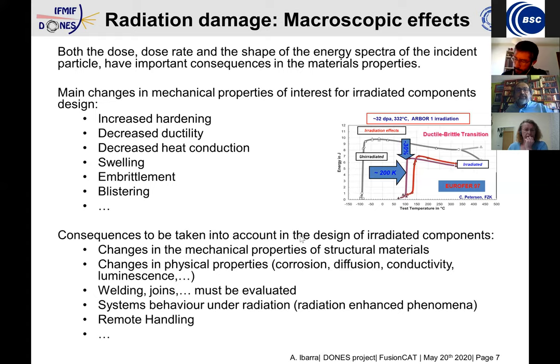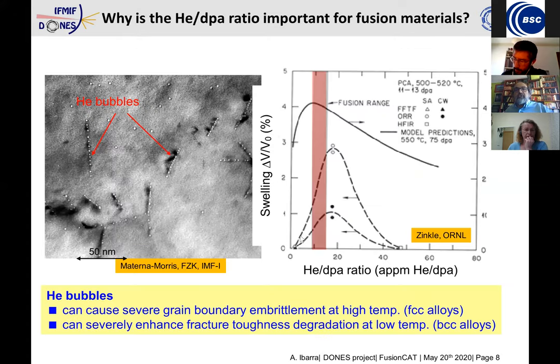So just going back a little bit to the fusion case, I will give you a couple of examples of properties that change due to radiation effects, and more specifically in the case of fusion. This is a very old example on the swelling of materials, and why the helium or hydrogen content is so important. Swelling is a property that measures the increase of volume due to the interaction of the radiation with the materials. You can see in the figure on the right that the swelling can be a few percent. That means a lot when you are designing a component.